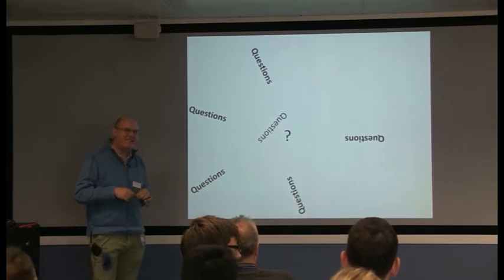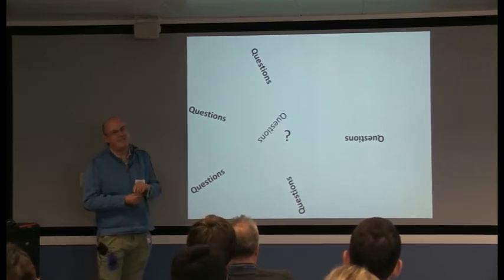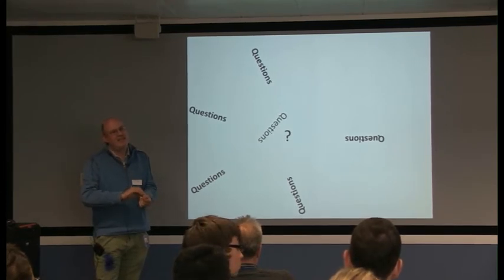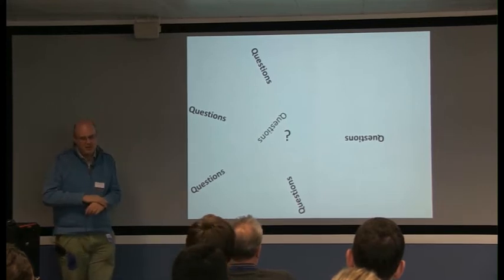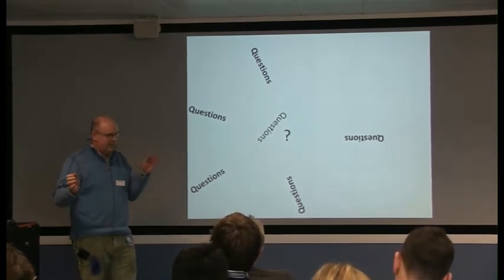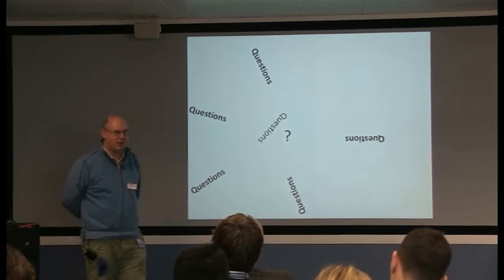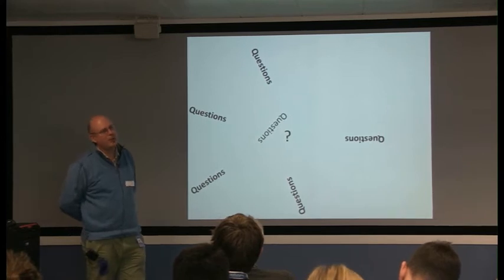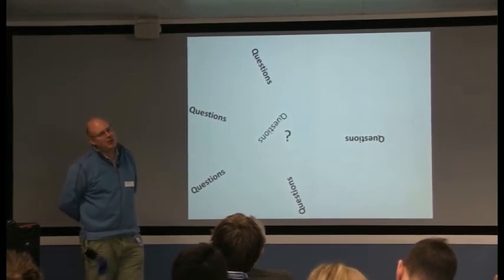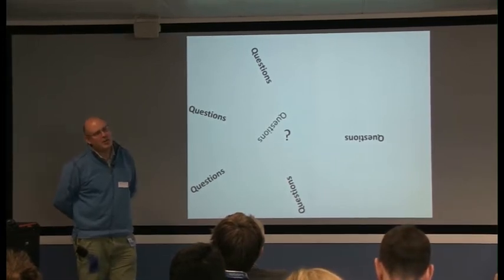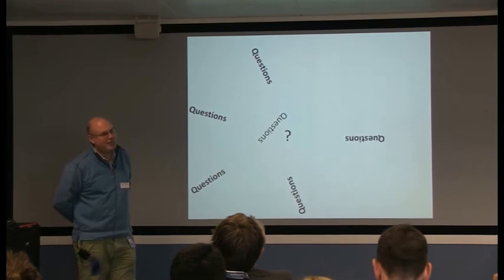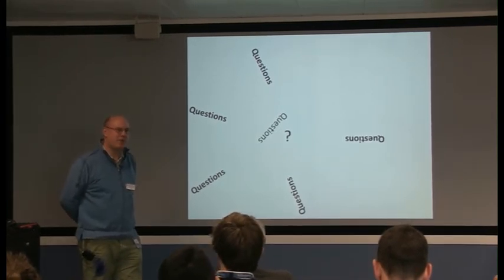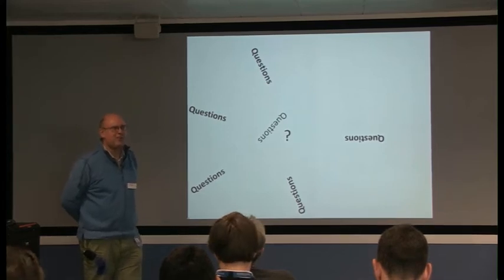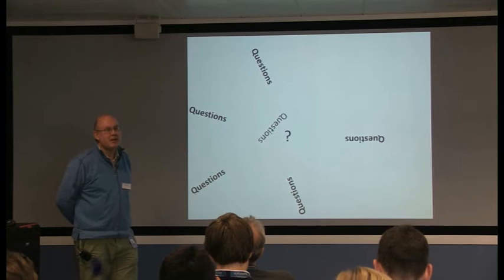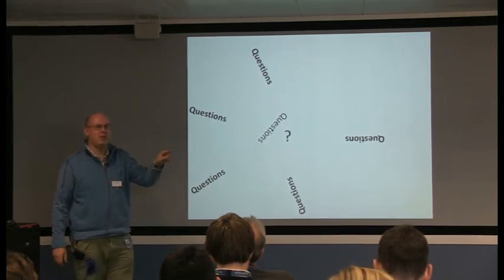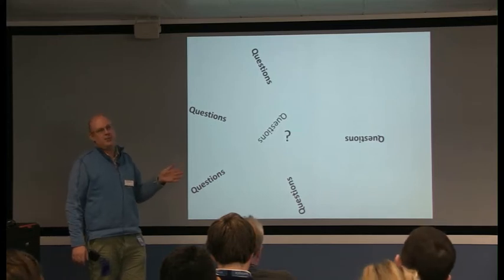Just a question - when you do the analysis in terms of preserving the oxidation states, do you normally do them at cryo? We tend to try and do some. For plant matter, yes, you almost have to do cryo, or bacteria type systems. For mineral type studies, we don't do a lot of cryo, but it depends a bit - some elements are much more photoreductive or photosensitive than others. Arsenic in particular is very photosensitive, manganese is photosensitive. Some elements are a bit more stable, but you can always test by just sitting at one energy point and seeing how the absorption changes - if you sit near the edge, that's the best way.